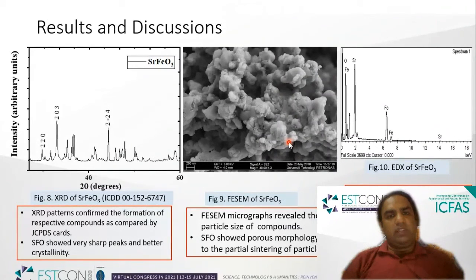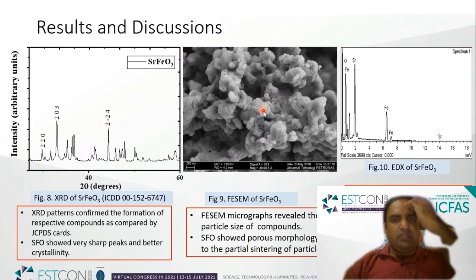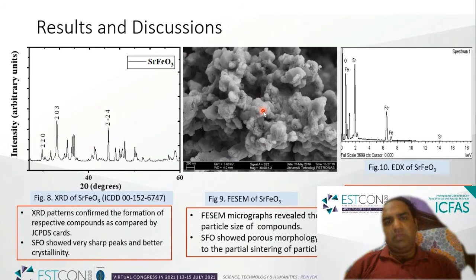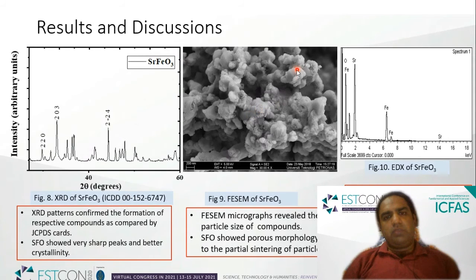So there are some results for XRD, FESEM, and EDX. The XRD results show the formation of strontium ferrite peaks, which are very sharp, showing high crystallinity, and when compared with the JCPDS cards, we get the exact results for strontium ferrite. For the FESEM, we obtained some agglomeration and a porous-like structure of the particles, which happens due to the combustion or partial sintering of the particles. We can see some of the particles attached to this porous material, but some of the particles were in the nanometer range. And then we have the EDX spectra of this strontium ferrite, which shows the elemental composition of these particles.